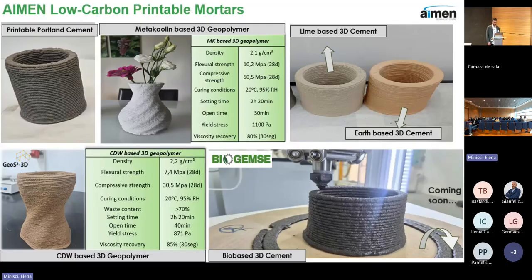And finally, in the Biogen project, as I said before, we are trying to optimize a bio-based 3D cement using biomass ashes. Well, we are very close. In this image, we are carrying out the collapse test, and the material withstood 25 layers. So we need to improve the buildability a little bit without compromising the open time and the suitability. But I hope in a few weeks or months we will have the final formulation.